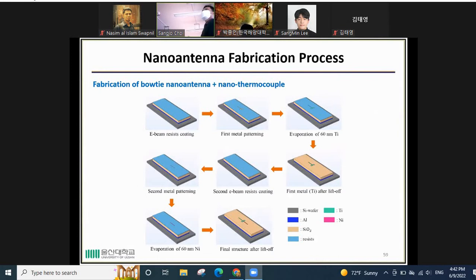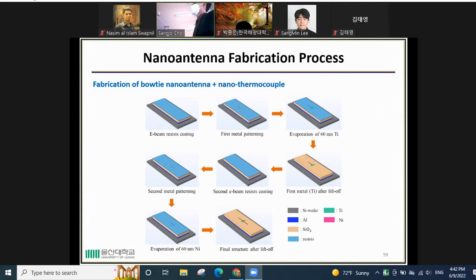And also this is the fabrication of both nano antenna and nanothermocouple. First, we coat the sample with the E-beam resist coating, and first metal patterning using E-beam lithography, and also first metal evaporation of 60 nanometer thickness of Ti. Ti is for the antenna. And then after lift off, the antenna is formed on the substrate. And then second E-beam resist coating, and also second metal patterning, and also evaporation of 60 nanometer nickel, and then this is the final structure after the lift off process. So we have a tiny nano antenna and nano thermocouple over the substrate.